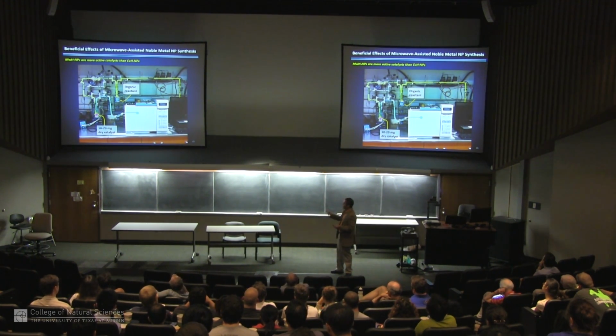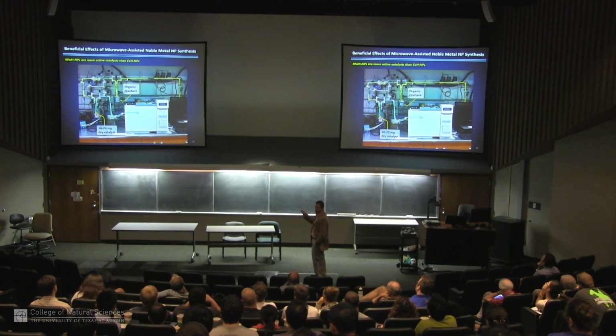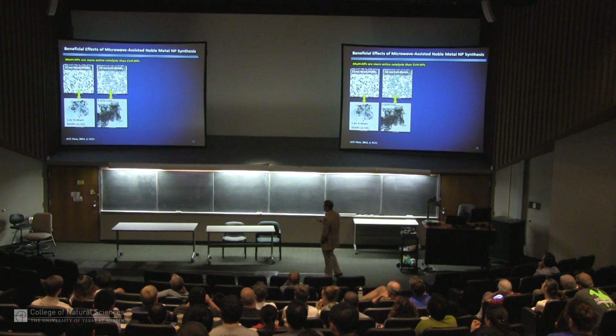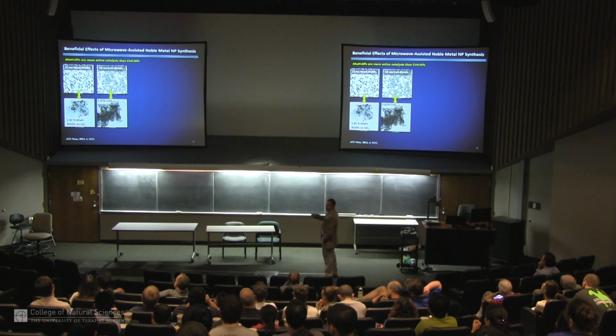And what this also means is we get kinetic information. So we can see how the catalyst changes over hours or days. And we're using a tiny amount of catalyst. This is 10 mg of catalyst, which is 1 weight % nanoparticles when we deposit these. And so this is a really tiny amount, nanomoles or nanograms of the metal. This is how we make the catalyst. It's pretty simple. We take our particles, we deposit them on silica or whatever other substrate we're interested in. This stops them agglomerating, it dilutes them, it allows us to handle the material.